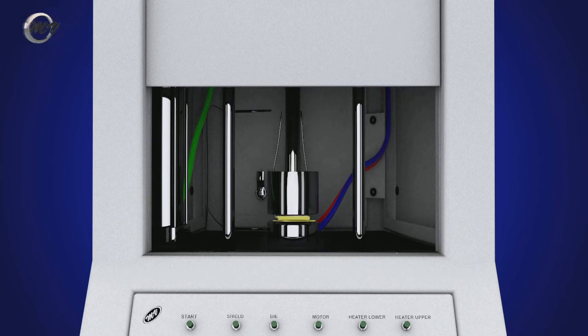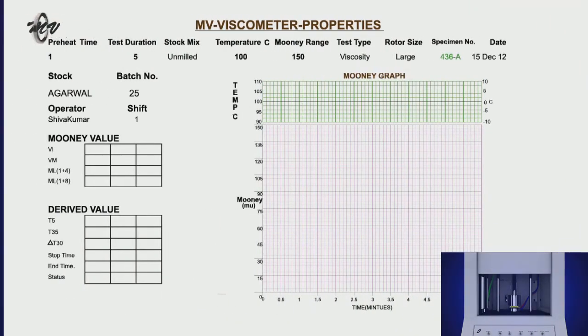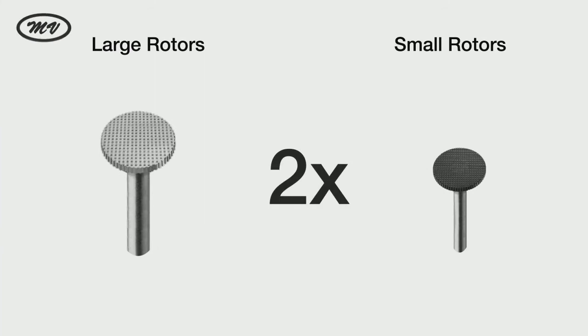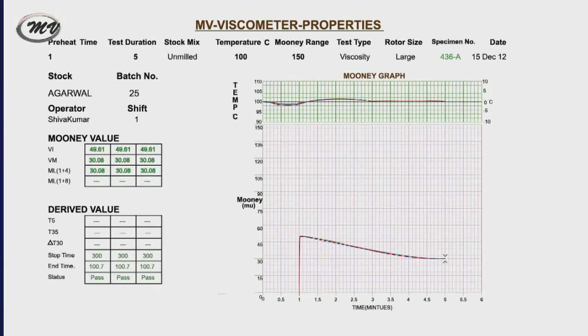The resistance to rotation offered by the elastomer is shearing viscosity, which is proportional to the mean absolute viscosity of the specimen. Normally, a preheat period is given to the elastomers, followed by which the disc starts to rotate. An initial high viscosity is recorded, and the viscosity decreases to a minimum value. Viscosity obtained with large rotors is approximately twice that of small rotors. The complete calibration can be performed directly by our software.